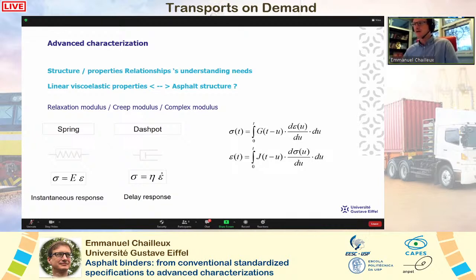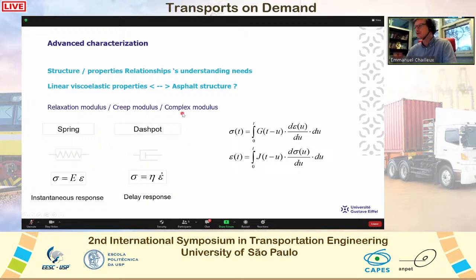So I don't know if you use linear viscoelastic measurements a lot, but you have to know that we can measure different types of properties, different types of modulus, with linear viscoelastic properties. We can measure the relaxation modulus, the creep modulus, but also the complex modulus. The behavior of a linear viscoelastic material can be represented by the association of a spring, where you have the stress to strain law, and a dashpot, where you have the stress to rate of strain law. Here we have the instantaneous response, here the delayed response.